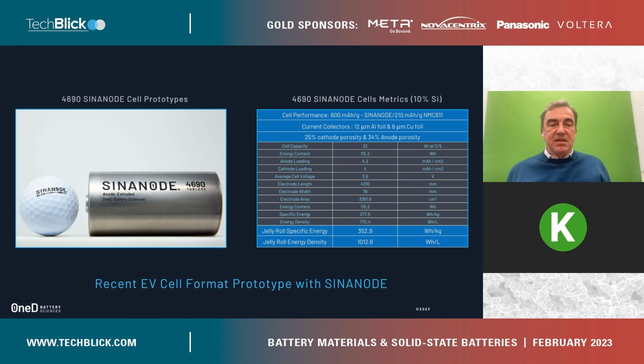And if you're on their website, they describe this. So we're not a cell maker, but we can ship them the powder and they can buy commercial cathode and make the electrodes. The electrodes in the 4690 cells are about 4 meters long, and they're being rolled, the cathode and the anode, in the jelly roll, and stuffed into the cells. And with only about 10% silicon, we can do more, but with only 10% silicon, we can achieve a reversible capacity in the anode of about 600 milliamp hours per gram.